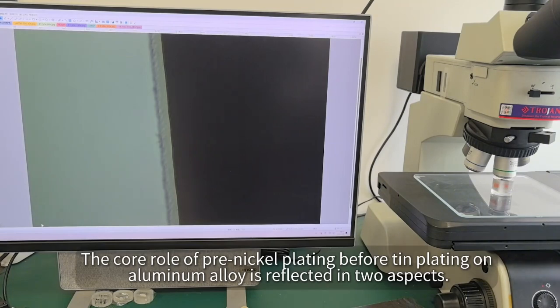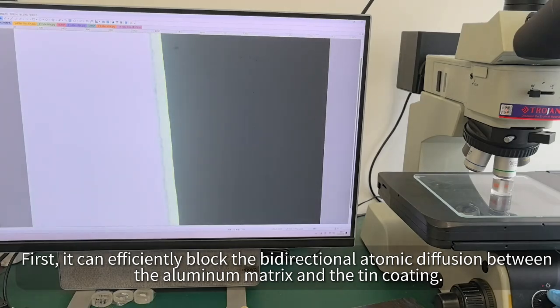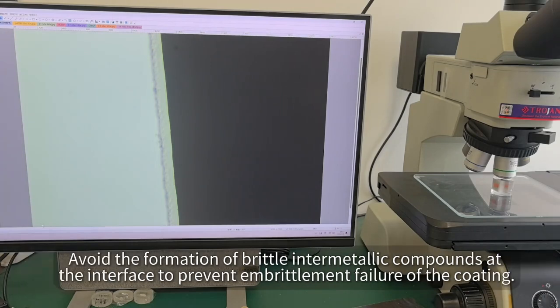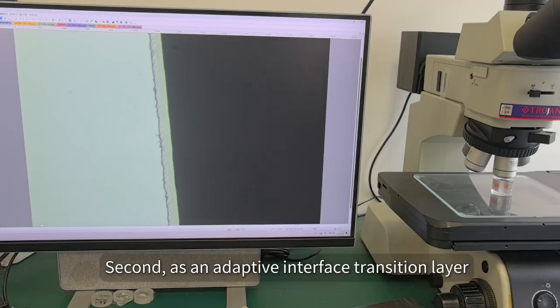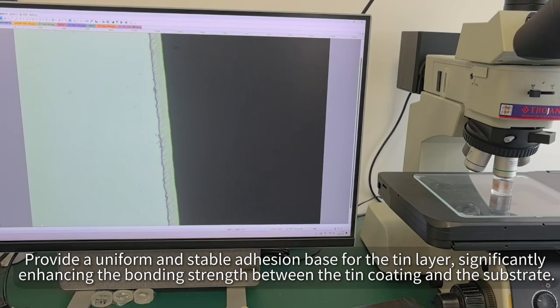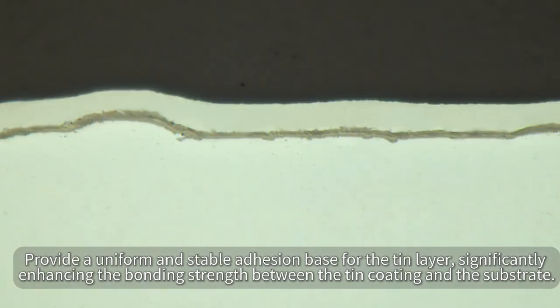The core role of pre-nickel plating before tin plating on aluminum alloy is reflected in 2 aspects. First, it can efficiently block the bidirectional atomic diffusion between the aluminum matrix and the tin coating, avoiding the formation of brittle intermetallic compounds at the interface to prevent embrittlement and failure of the coating. Second, as an adaptive interface transition layer, it provides a uniform and stable adhesion base for the tin layer, significantly enhancing the bonding strength between the tin coating and the substrate.